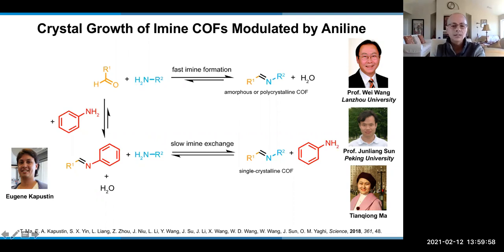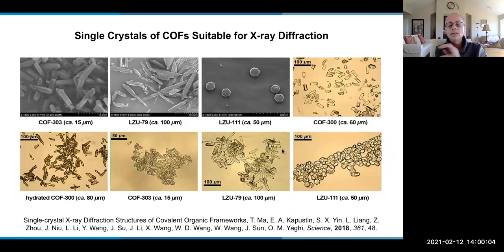You do have to wait many, many days, I think 30 days or 40 days in some cases, to make those single crystals. But once you make them, you don't need to wait anymore because now you know what the structure is. So from a single crystal point of view, these are giant crystals that have been characterized by routine X-ray diffraction in an in-house instrument. You can see here that as you add more and more aniline, your crystals get larger. So these are the first single crystals of COFs that are amenable for single crystal X-ray diffraction.